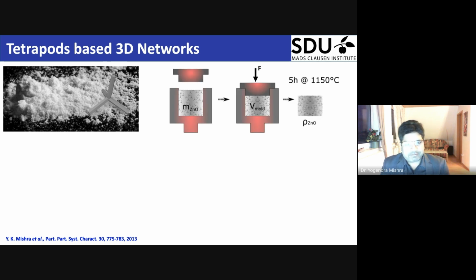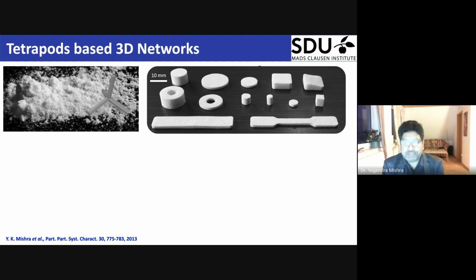What I did with the complex thing was to give an advantage to such porosity, the more complex arms being quite large. So we put these tetrapods, with their self-assembly feature, in a mold with a well-defined formula, and then we decided to control the density. In this way, we basically construct the architecture inside of how each set comes together. One can apply chemicals, one can apply several things, but I used the hard way: a high temperature of 1150 centigrade for 5 hours. This allows the formation of these three-dimensional networks in a very nice way, in any shape or any size.